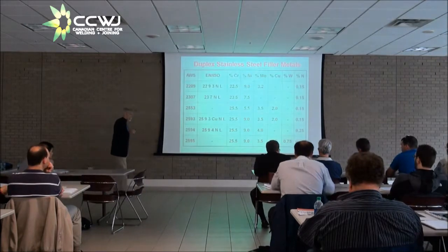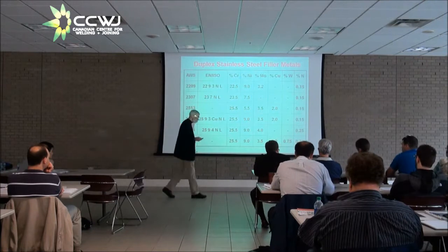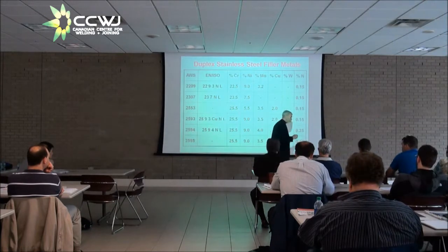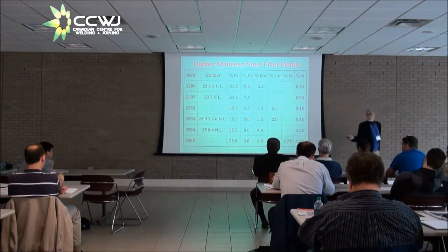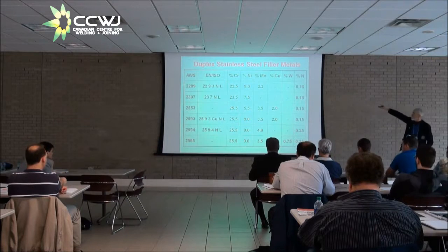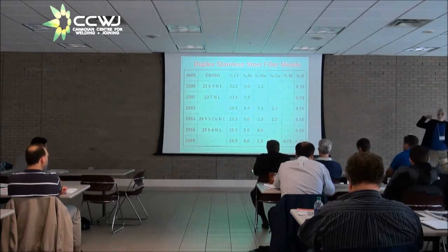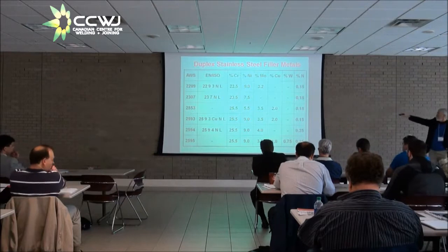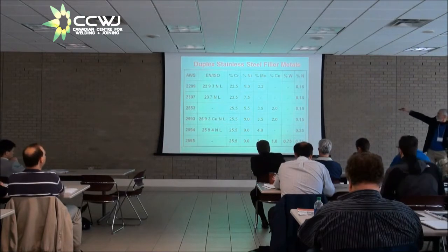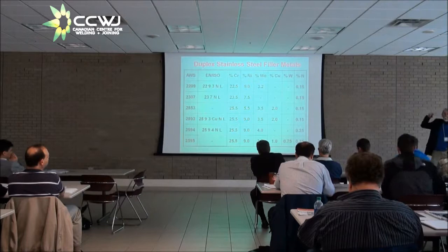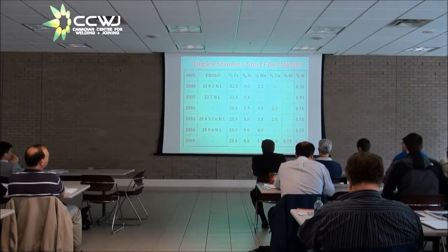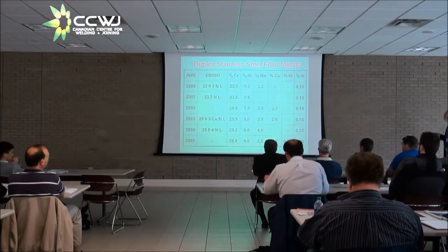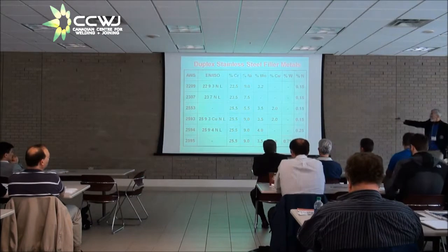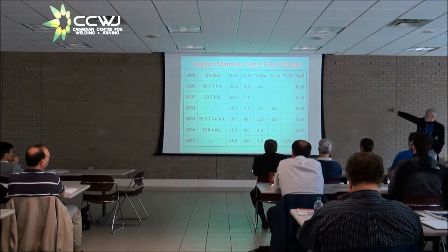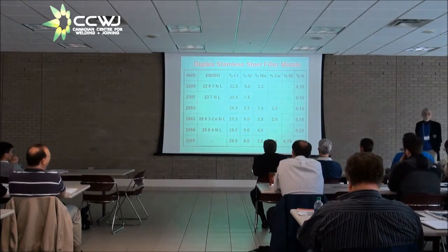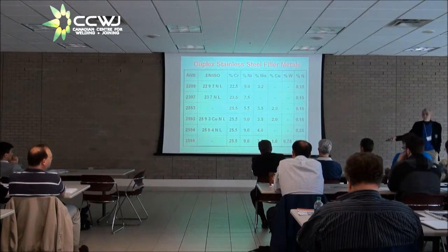Filler metals for these are classified both by AWS and in the ISO standards. What you see in AWS is 2209, which is directed at 2205 type base material. The 2307 is intended for the lean duplexes. The alloy was originally developed for 2101, but it also works for 2304. That alloy is quite different in composition. It has quite a bit of nickel compared to the 2101 base material.